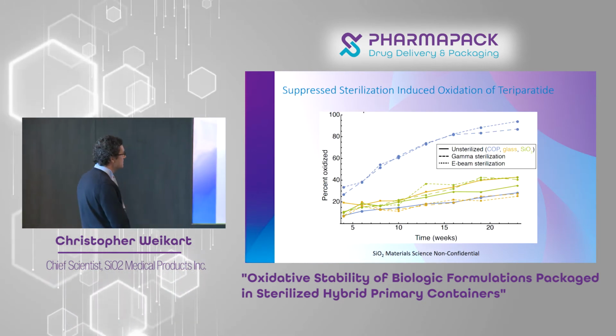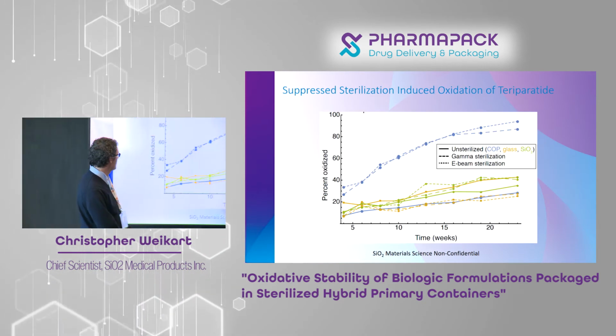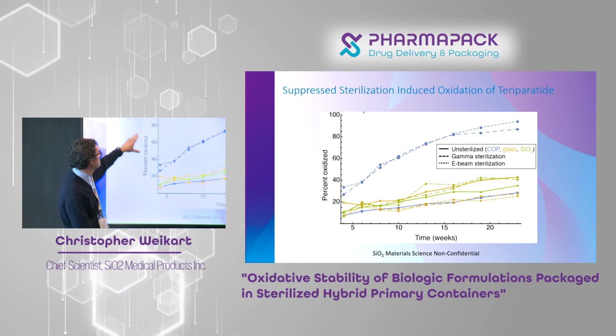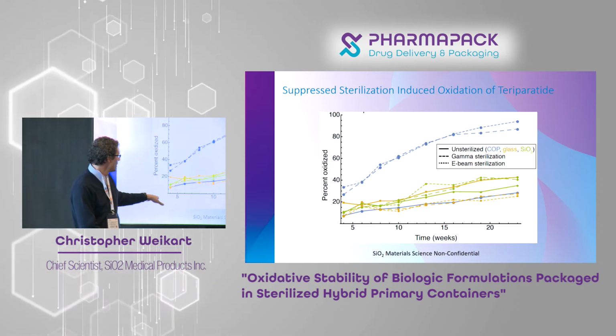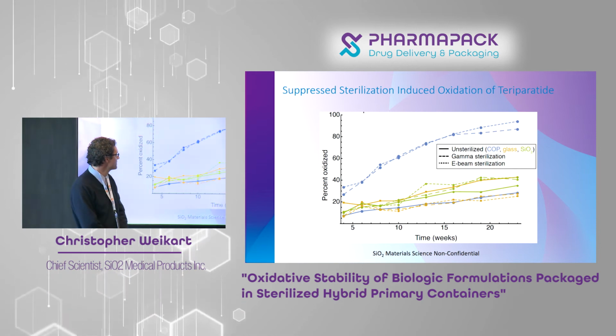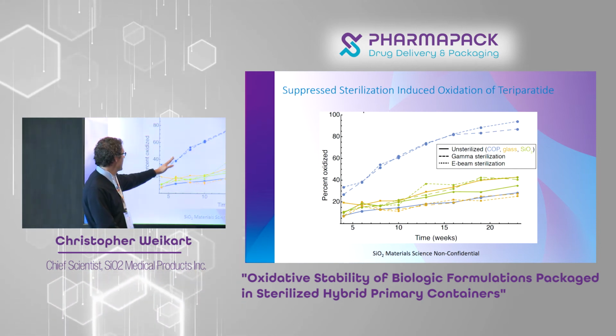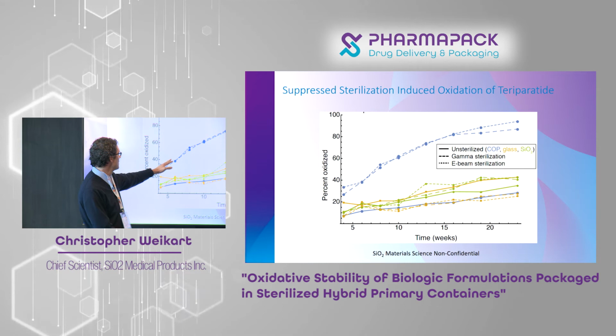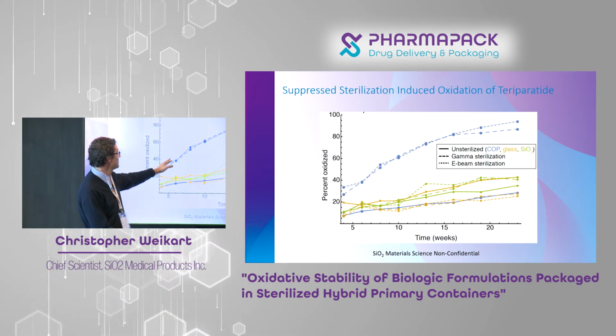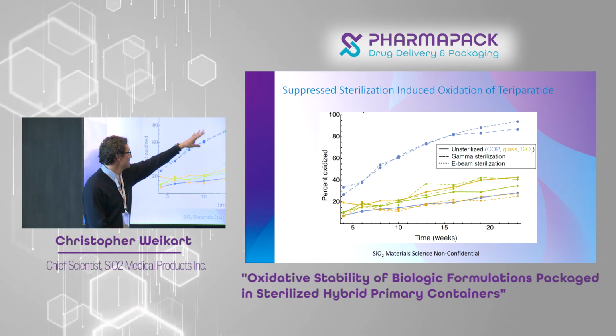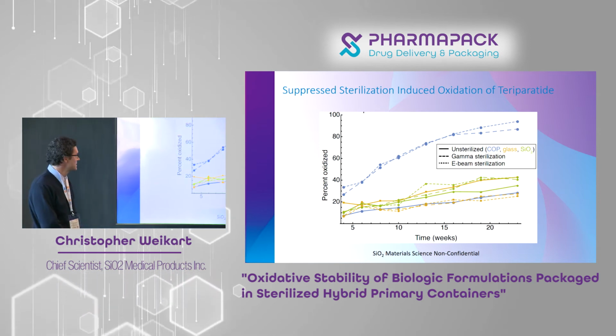Okay, so these are results. What you see here basically is percent oxidation of teriparatide over the course of 25 weeks. And you can clearly see gamma and E-beam sterilization of a COP container containing teriparatide. You can see the oxidation occurring, not surprising.